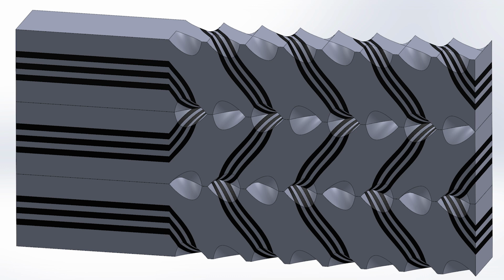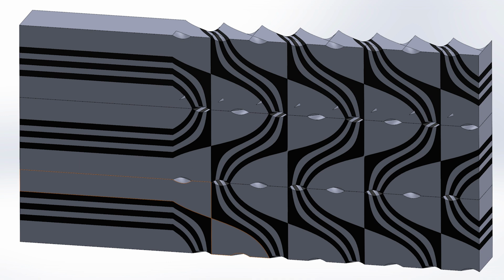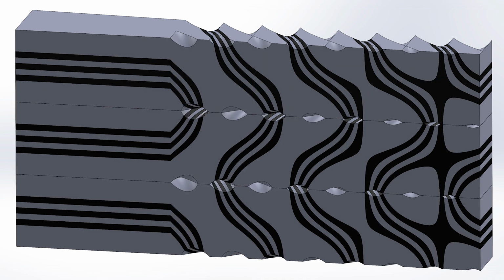Sometimes the slanting of the pattern goes in one direction and sometimes in the other. For clarity, let's go back to the chevron straight pattern and rebuild it in SolidWorks. This one here represents a 5 to 10% grind, and this is the 25% grind. And finally something that resembles the original blade, with the grinding started at 10% and progressing up to 30%.